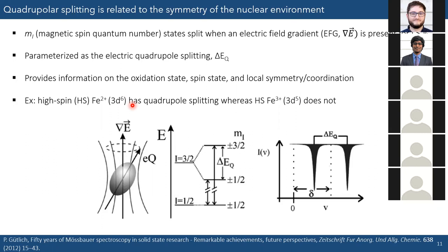Wonderful. Thank you. Whereas if you're looking at low spin iron 2+, now there's going to be 6 total electrons in the three lowest energy d orbitals, which are our T2g orbitals. These are each going to now have two electrons in them. And so that's going to effectively create a homogeneous electric field for our nucleus. And therefore, we're not going to observe quadrupolar splitting for low spin iron 2+.